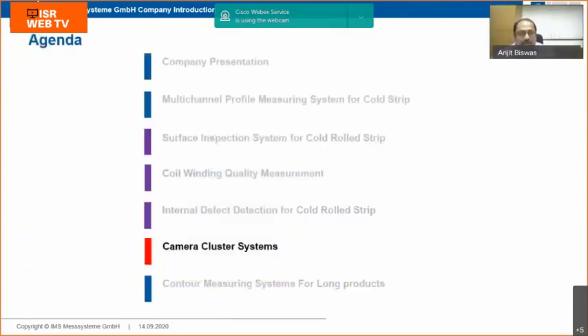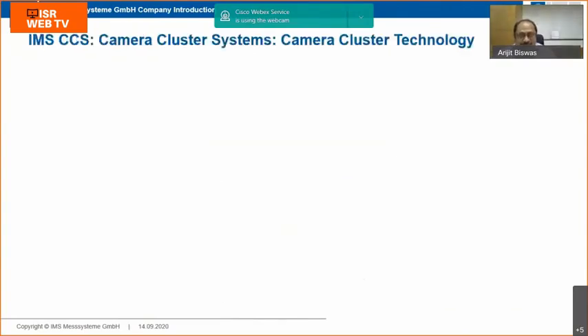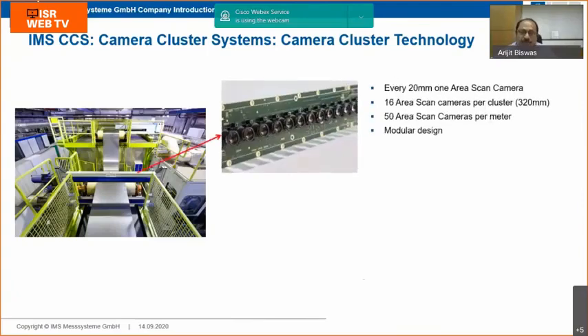The next important and patented technology is the camera cluster system. We know that for width measurement, in the past and even now, we have been using two cameras to measure the width of the strip. But in this camera cluster technology, we are using a cluster of cameras. Each camera, from diameter to diameter, is situated at a 20 mm distance. So from one camera to the next, it's just 20 mm. These cameras are put in a cluster where we put 16 cameras together, covering around 320 mm. Depending upon the width of the material, we decide the number of camera clusters to be used.